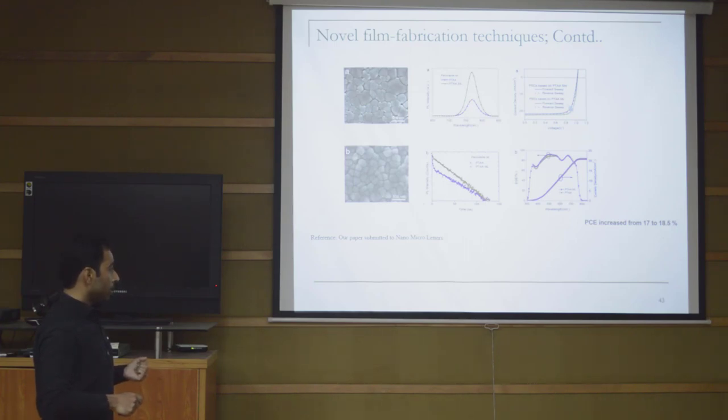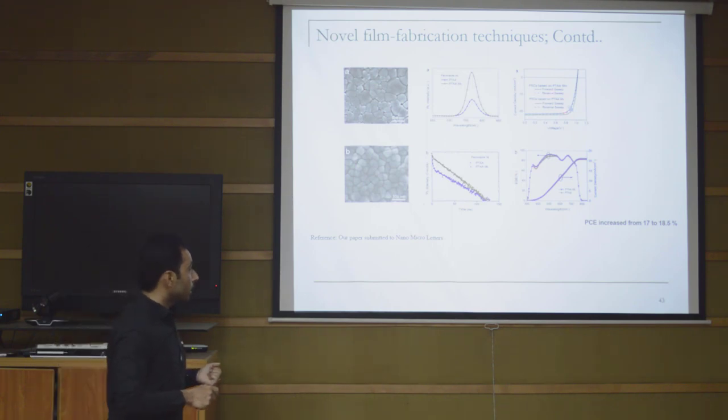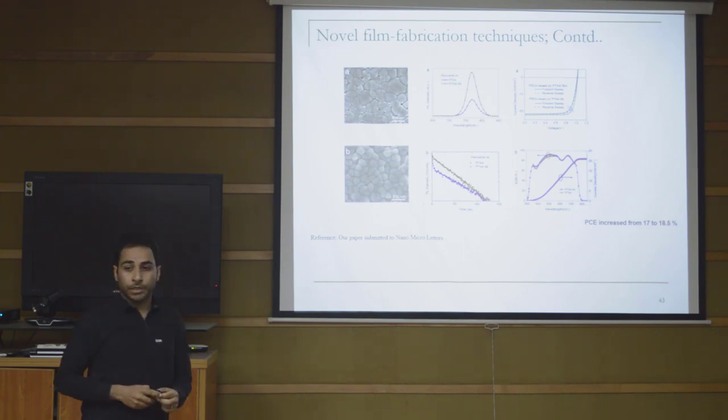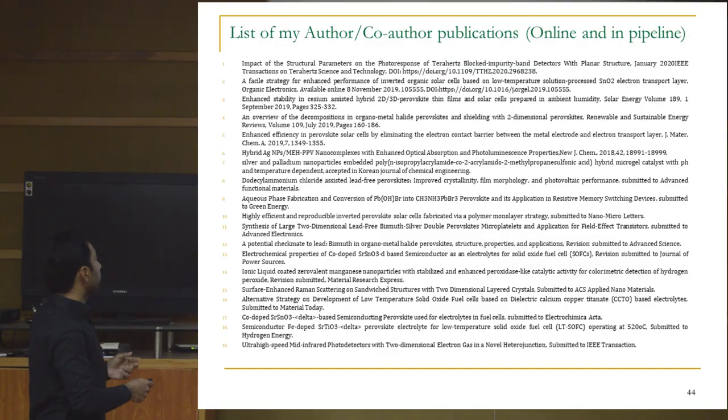Also, the PL intensity and lifetime increased. The device characteristics increased—IV characteristics, EQE, and current density—everything increased. The efficiency was about 17% but increased to 18.5%.